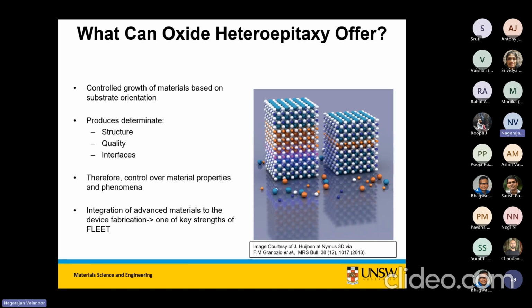The other thing that we can do, and I was talking at lunch about it, I don't have a slide here, is that not everything has to be a film. When we first started growing bismuth ferrite, we were struggling like everybody else, and we used to keep getting these iron oxide pockets, right? So as a typical PhD supervisor, I was just driving my student crazy, saying I want perfectly smooth bismuth ferrite films. So we got to work on that.